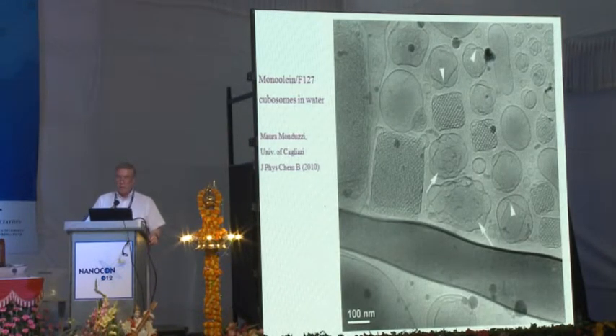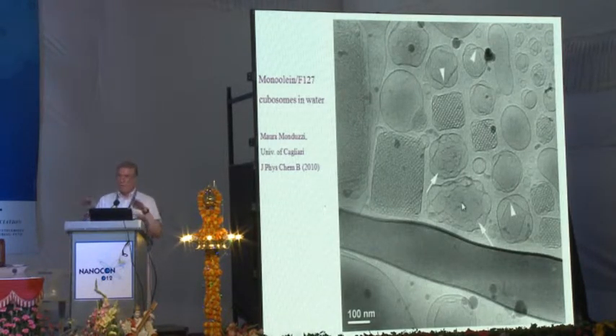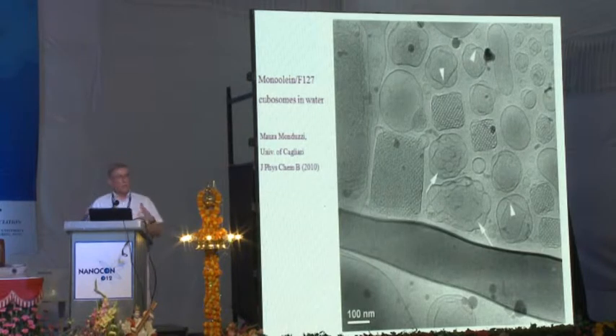You see here on the screen 3 different types of structures. You have this one here where the cursor is, this is a lamellar phase. You see this thing here, which is a cubic phase, a liquid crystalline cubic phase. And then you have the intermediate, which is this thing here with the white arrows. So in one field of view, we have 3 different phases, all clearly seen by the electron microscope. This is really one of the main advantages of electron microscopy, that you don't need a model to interpret your data. And especially when you have a mixed system or a system with a very broad size distribution, it would be very difficult to interpret the data if you didn't have a direct image like this.